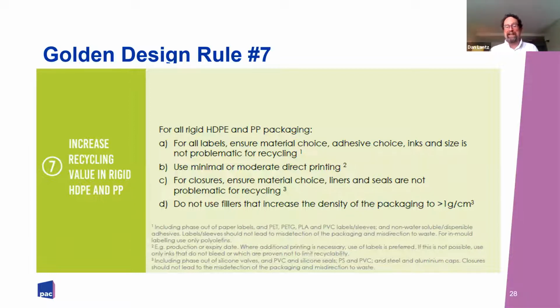The other thing that's really big on this category is don't use fillers that increase the density of the packaging to greater than 1 gram per cubic centimeter. In fact, don't use fillers even if they don't increase the density of the packaging to greater than 1. This applies for other, like that light blue thermoform I showed you earlier. That was actually a PET thermoform, but that PET thermoform had 40% calcium carbonate in it. Now, PET's already got a density greater than 1 gram per cubic centimeter, so it's already going to sink. However, the calcium carbonate at 40%, even 10%, you think about it, calcium carbonate is not plastic. Calcium carbonate is stone. You can't make plastic out of stone. Calcium carbonate is a contaminant that makes that package not recyclable.